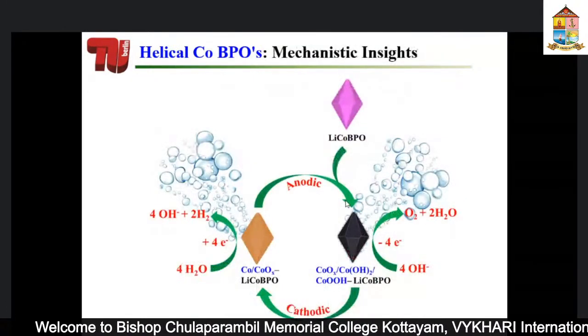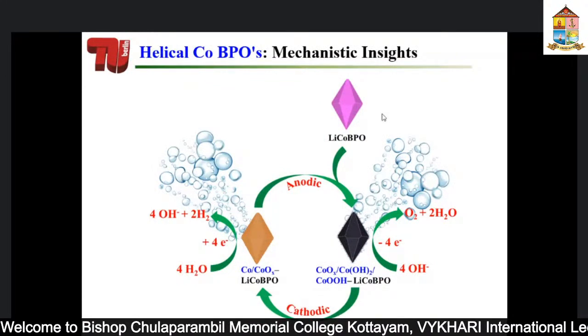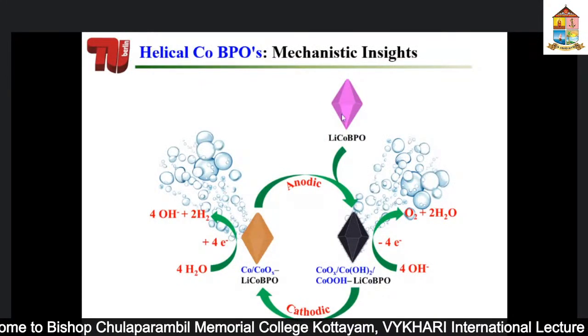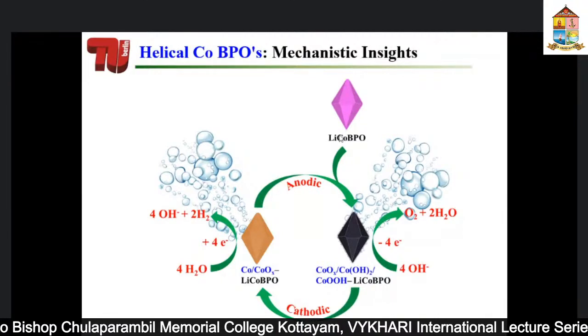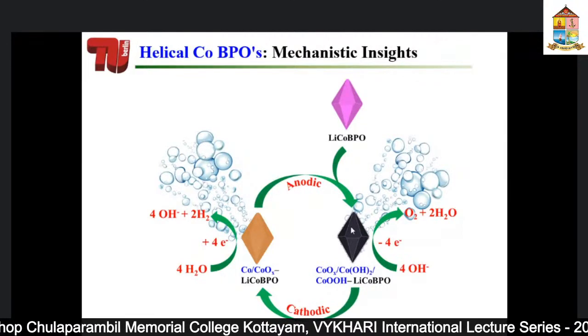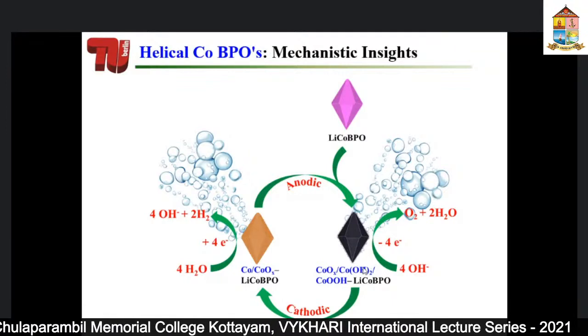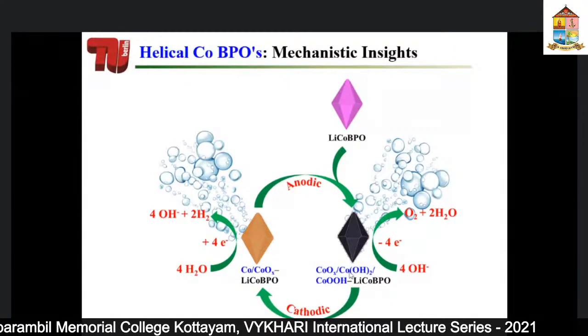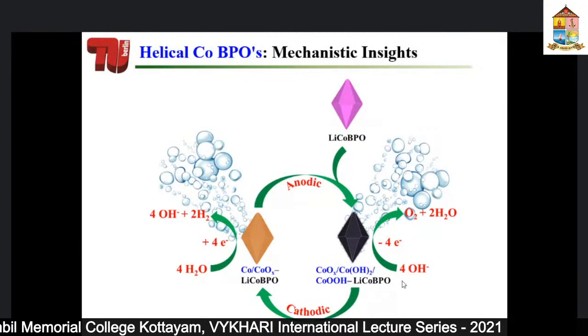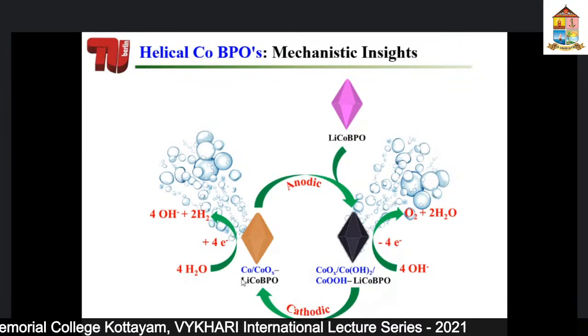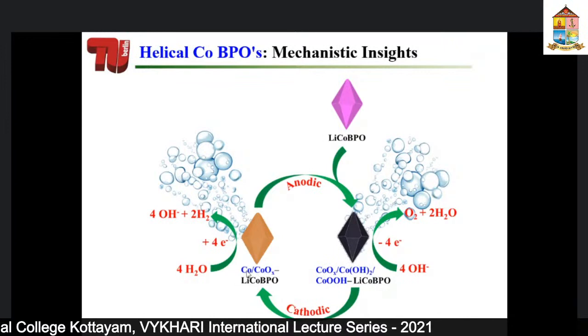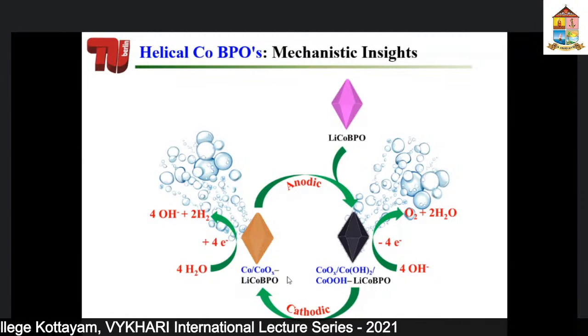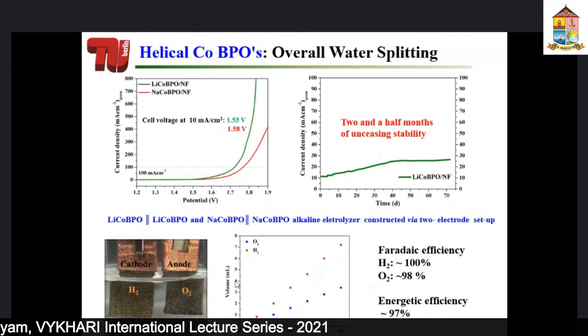Okay, so to show you what we learned from it, we have prepared a cobalt borophosphate, which typically I show for lithium, and it changes immediately. We apply the potential to produce the oxygen evolution reaction, forming hydroxide, oxyhydroxide, oxide on top of cobalt borophosphate. Similarly, if you apply negative potential, what you gain is metallic cobalt on the surface with some amount of cobalt oxide on top of lithium cobalt borophosphate.